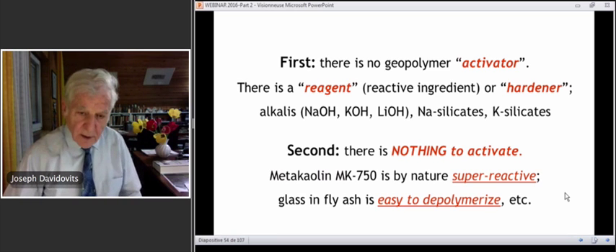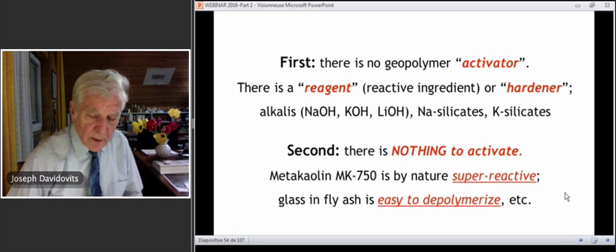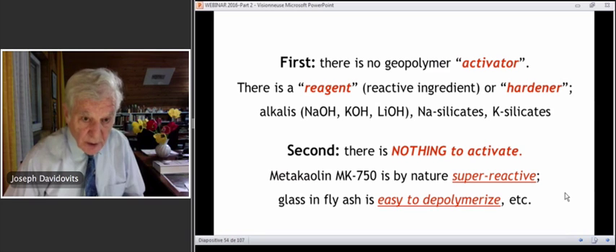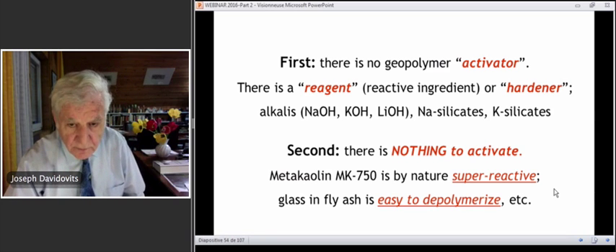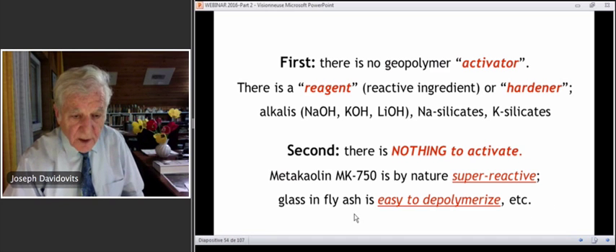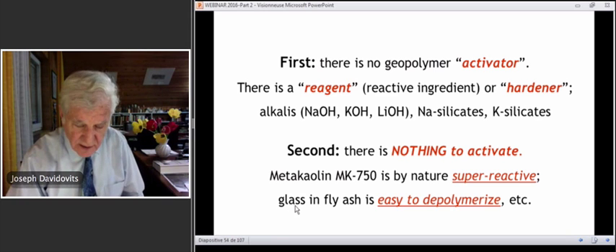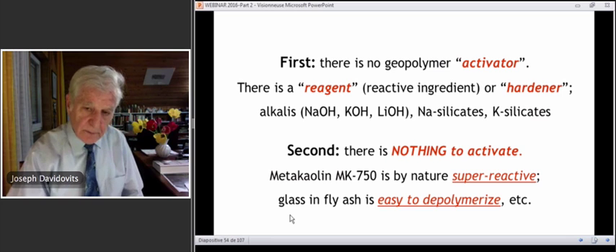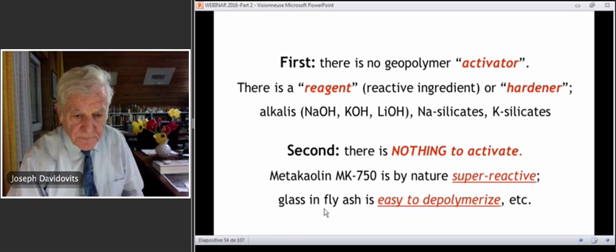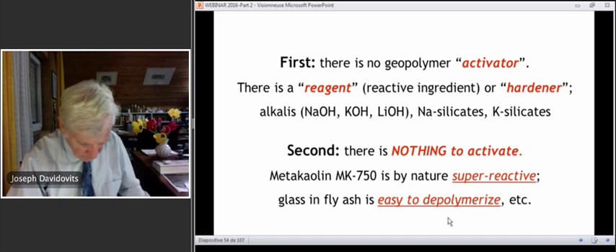The double bond, the aluminum oxyl group is there. It is, from a chemical point of view, a reactive material. We don't have to activate it. As far as fly ash, 80% of the fly ash is made of glass, and it is the quality of this glass which gives the potential in terms of geopolymerization. The glass is very easy to depolymerize. You don't have to activate the glass, it just reacts with alkali, with the sodium silicate, and so forth. These are wordings that are totally misleading and wrong.